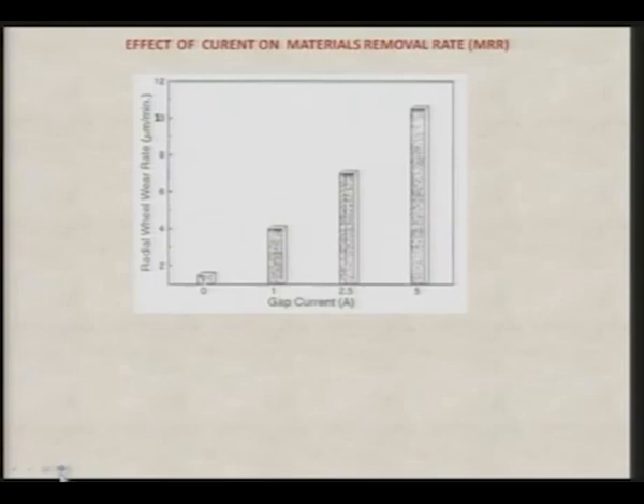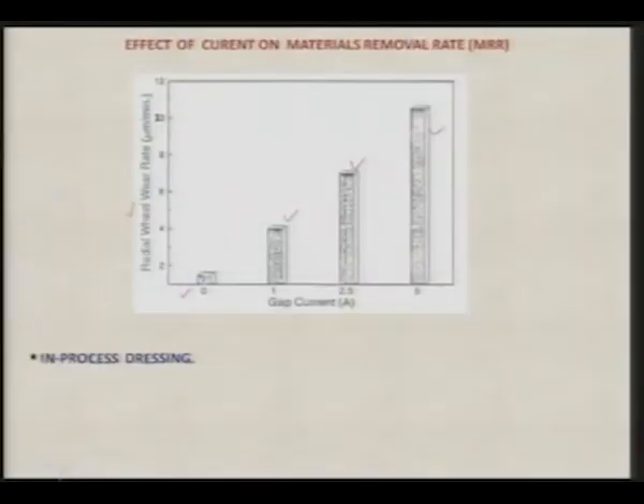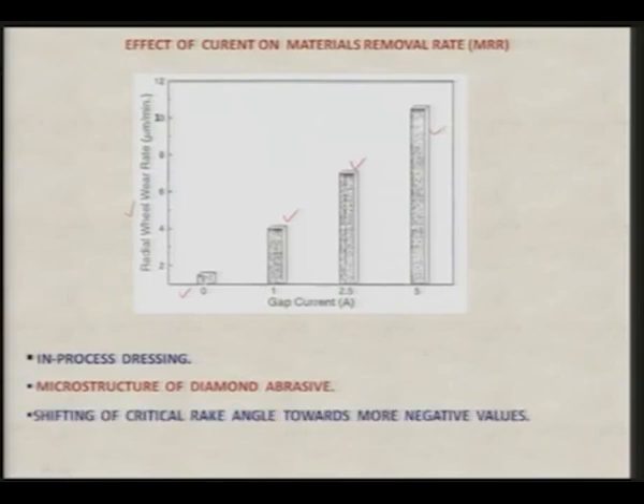Now, effect of current on material removal rate: we can see at 0 current in the gap, the material removal rate is very low, while as the current is increasing, 1 ampere, 2.5 ampere and 5 ampere, it is continuously increasing. And radial wheel wear is another important parameter which decides the total wheel life, and this should be minimum. So, here you can see, as the current is increasing, the radial wheel wear is also increasing, in terms of micrometer per minute. In process dressing is taking place continuously in this particular case. Regarding the microstructure of the diamond abrasive particle, shifting of critical rake angle towards more negative values takes place during this electric discharge diamond grinding.